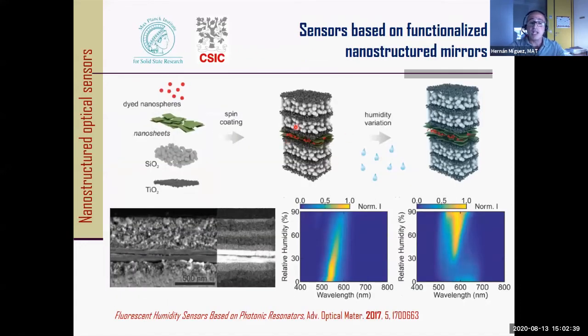We have a well-defined optical resonance, and we can get a strong emission from these dye spheres here, right? So we get a very strong emission of light. But if I expose this to humidity, the nanosheets are going to start increasing in size. They swell. And as they swell and I change the geometry of the whole structure, this intense emission that I was talking about will no longer happen.